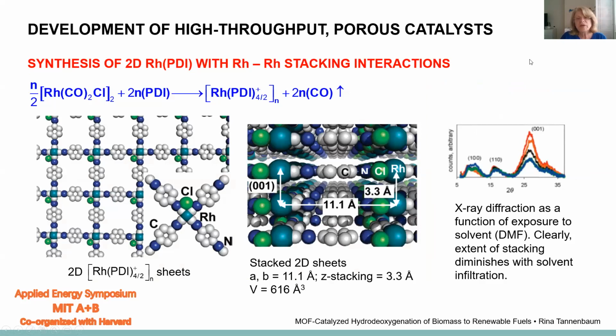The next complex that we can look at is the rhodium complex. So with the rhodium complex, we have the rhodium carbonyl reacting with the PDI ligand to form the square planar, exactly like in the picture. Here's the rhodium in the middle. And here is the rendering of the arrangement of the rhodium complex sheets in the Z direction. And what we see is that we have a stacking of the rhodium atoms. And we see this is the 0, 0, 1 direction in the Z direction. This is the X-ray diffraction corresponding to this distance that is typical of stacking interactions.